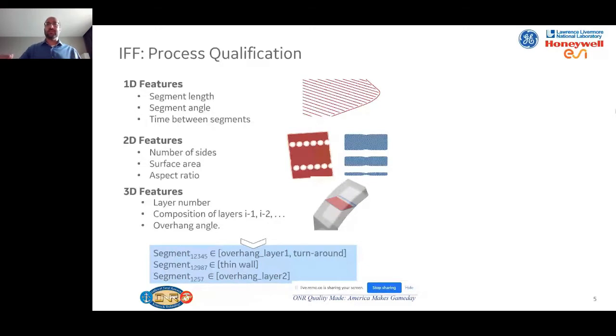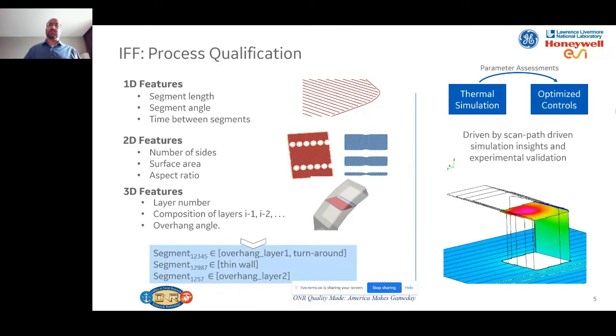And to help accelerate this, we really started tying in simulation capabilities. And so for this example, we're taking intelligent feed forward capabilities for scan path control, and we're leveraging thermal simulations developed by ESI in association with Honeywell to look at strike-by-strike based material response of a geometry and see what the thermal response looks like for that part. And so for this example, we're actually looking at individual strikes being associated to it that are actually the IFF outputs to see how the thermal response changes, in this case, in regards to the overhang area, but also the length that you are into an overhang, and see what the thermal variation really can look like, and allows us to identify if this is a feature that matters and how much so, and how to go about controlling it. So we're able to pull thermal simulations to have optimized control during our process qualification stage.